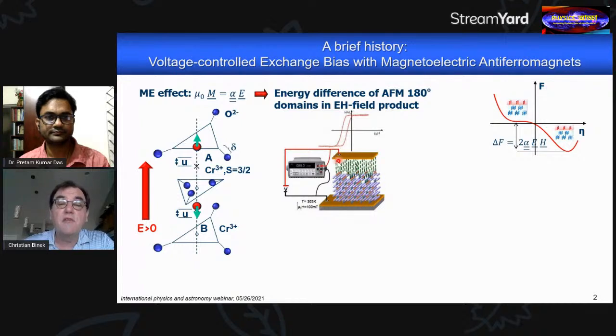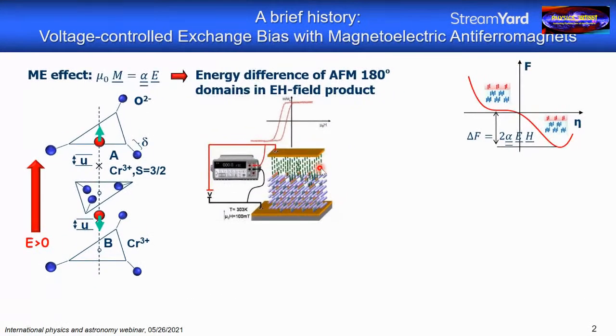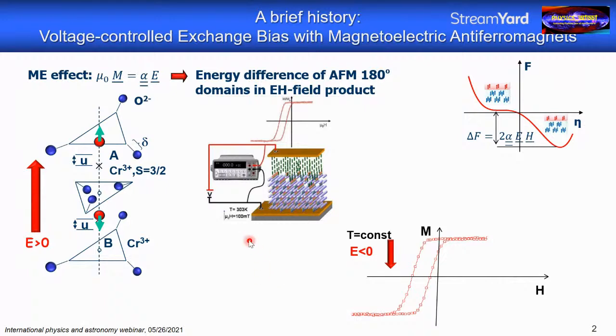Now that is what we use in a voltage-controlled exchange bias heterostructure. So here you see a cartoon where we have this antiferromagnetic system, and a ferromagnet is deposited, in our case, by molecular beam epitaxy here on top of that antiferromagnet, and there's exchange coupling at the interface between the magnetization of the perpendicular anisotropic ferromagnet and the boundary magnetization of the antiferromagnet. And now, in the presence, and that's the catch to some extent, in the presence of a magnetic field which can point in one direction, we don't have to change it, but it has to be present, we can now switch the hysteresis curve of this ferromagnet on top.